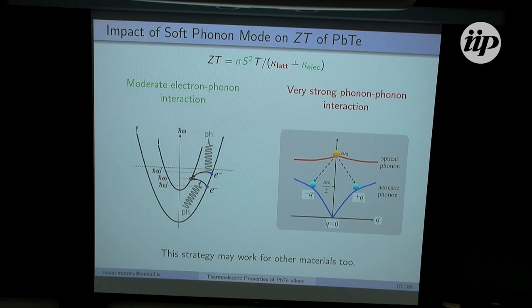So the hope here is that as we get near the phase transition, electronic properties will not be that negatively affected, but even if they are, the gains we make in the reduction of the lattice thermal conductivity will far outweigh it, potentially greatly enhancing the figure of merit. And just to briefly mention as well, this isn't specific to lead telluride. This strategy could work on really any material with a similar soft mode phase transition.